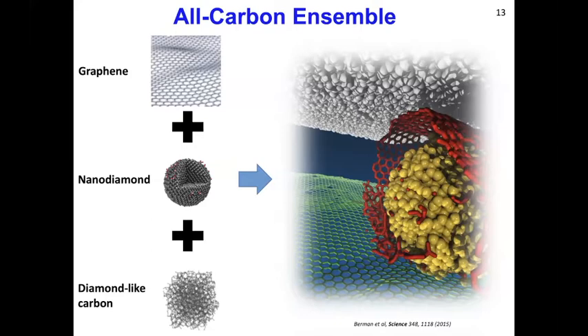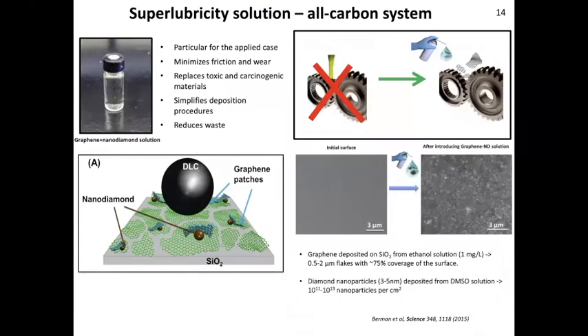And how it actually happened, we demonstrated that we can reach the superlubricity regime using this all-carbon ensemble system, using graphene, as we already observed, using diamond nanoparticles as surface separators, allowing us to minimize the area of contact, and then using diamond-like carbon, or DLC, to provide this perfectly incommensurable state to avoid any structural interlocking in our systems.